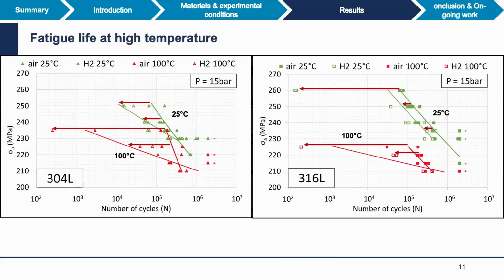Now, the same type of comparison, so the same data at room temperature compared to the data at 100 degrees C. And what is somehow surprising is that we have the same type of observation. That means that we have almost no effect of hydrogen at low stress amplitude. But if we increase this value, we have a significant loss in fatigue resistance, and this holds for the two grades. And this is quite puzzling to me up to now. I have no clear explanation.